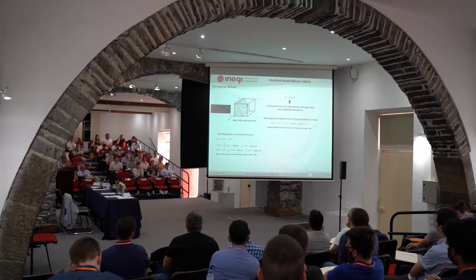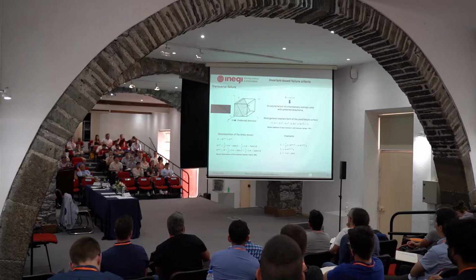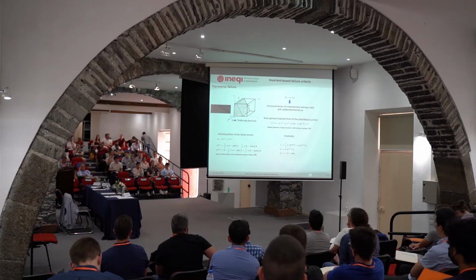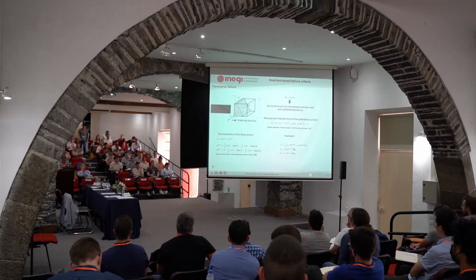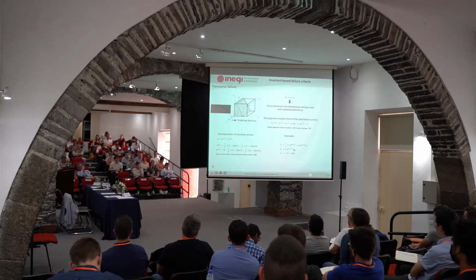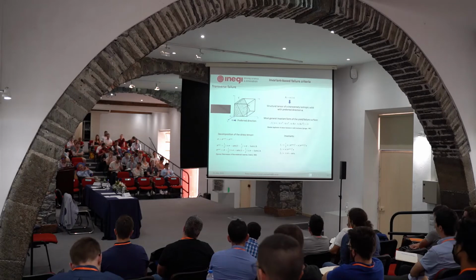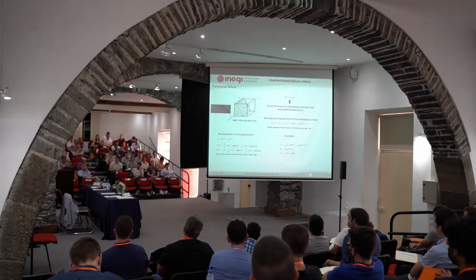Okay, so with that, what we can do is to propose the three invariants that are again scalar functions of the stress tensor that will drive failure. Okay, so the first one you'll see in a moment. This is the first invariant that we propose to capture failure under transverse shear. This one under in-plane shear, and we have to introduce this one here because composite materials are frictional materials, so we do get an effect of hydrostatic pressure in the conditions that trigger failure.